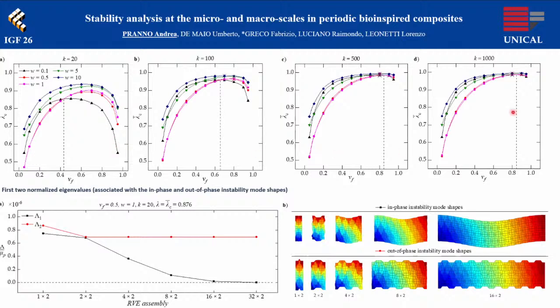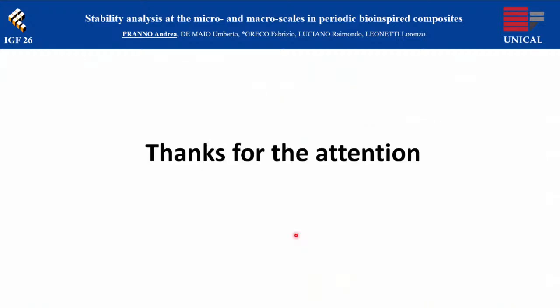In addition, high shear modulus contrast experiences macroscopic instabilities at lower uniaxial compressive loading, which correspond to a higher critical stretch ratio. For the investigated range of geometrical and material parameters, the instabilities are found to be global with an in-phase mode shape. It was also obtained that out-of-phase instability mode shapes occur at a significantly higher magnitude of homogenized energy compared to the in-phase one. The results indicate that adopting a small unit cell assembly, the microscopic stability analysis provides, in most cases, strong underestimates of the critical stretch ratio, and that an accurate stability prediction can instead be obtained by monitoring the strong ellipticity condition, which is computationally less expensive than a rigorous macroscopic stability analysis. Thank you for the attention.